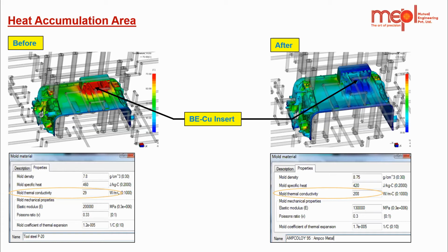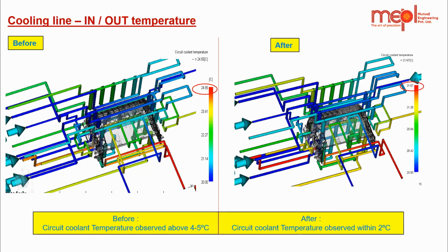To overcome this issue, we used the BeCu insert, a beryllium copper insert. As you can see, the mold thermal conductivity was very high, so it reduced the temperature of the mold. After the cooling lines we used, the coolant temperature difference which we observed before was high, like 4 to 5 degrees. After changing the cooling lines and using the beryllium copper insert, we can achieve the desired cooling temperature within 2 degrees Celsius.